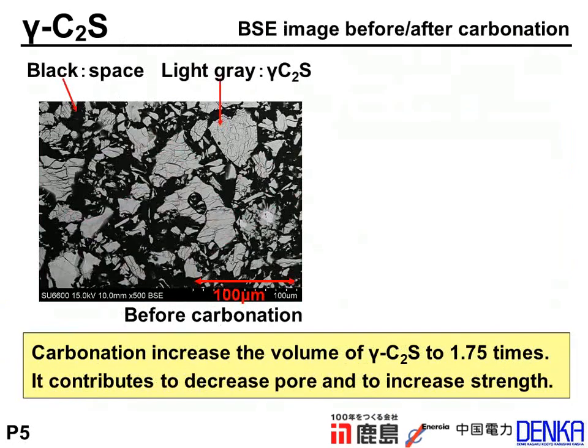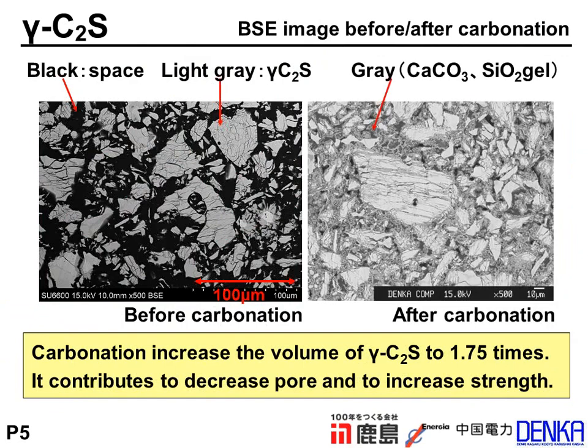So this picture is the backscattered electron image of gamma C2S before carbonation. These particles are gamma C2S, and the black part is particle space. The right figure is the picture after carbonation. You can see that the black part decreased and was filled by gray substance.